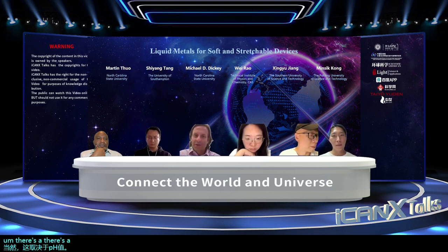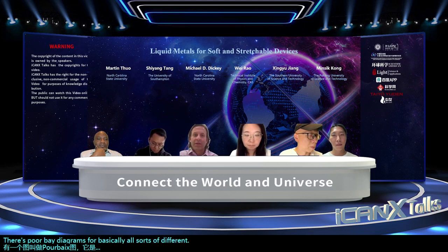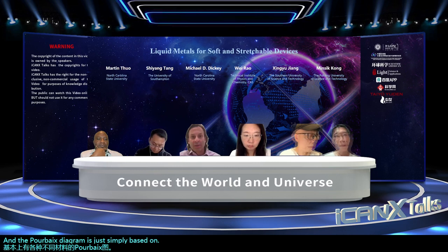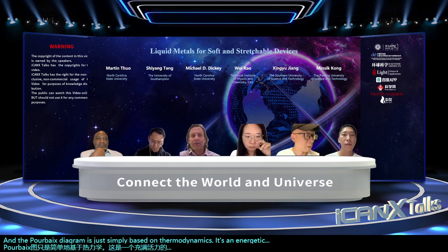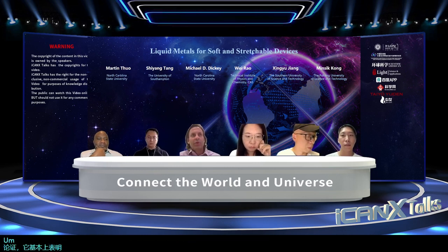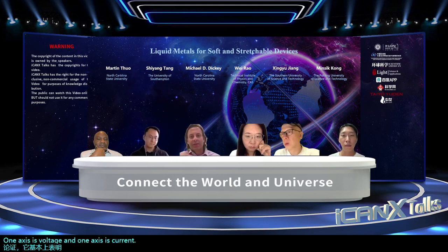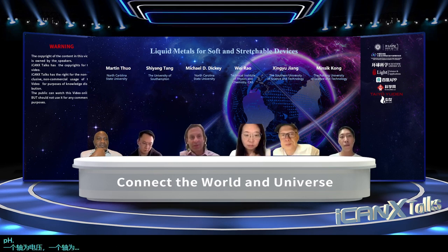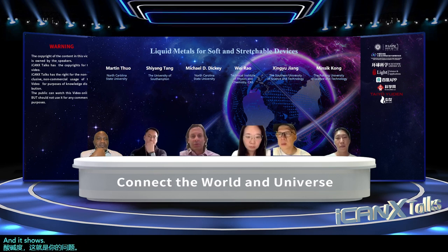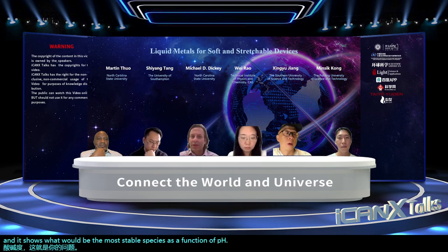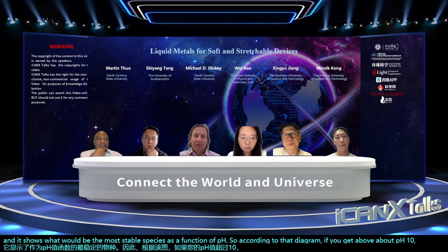There's a diagram that's called the Pourbaix diagram, and there are Pourbaix diagrams for basically all sorts of different materials. The Pourbaix diagram is simply based on thermodynamics. It's an energetic argument, and it shows one axis is voltage and one axis is pH, which gets to your question. It shows what would be the most stable species as a function of pH. So according to that diagram, if you get above about pH 10, the oxide should be unstable.